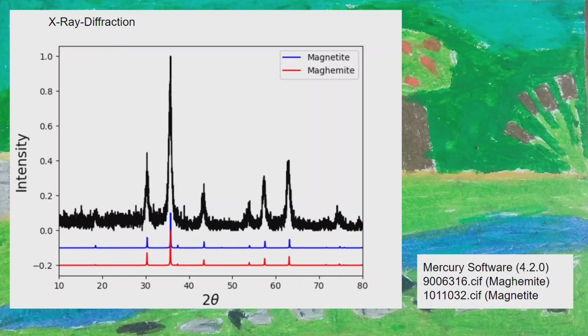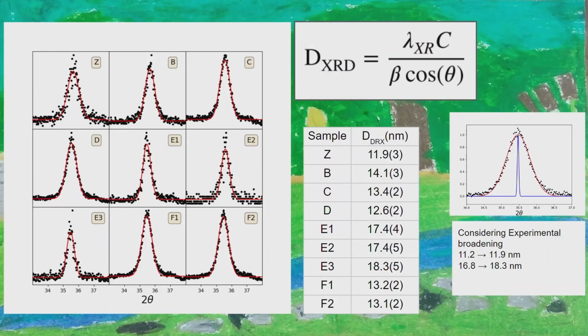Not all, but almost all of them were characterized by X-ray diffraction, and we don't see any presence, only magnetite and maghemite. We don't have easy access to X-ray diffraction, but we wanted to know about the diameter because we were discussing whether they were bigger or not. So we concentrated on the main peak, and we can obtain diameters from this main peak. Here is only a consideration about whether you take experimental broadening into account or not. It's important, it makes a change. It makes big changes in bigger particles, where the peaks are narrower, and maybe not so important in smaller ones, but you have to take it into account.